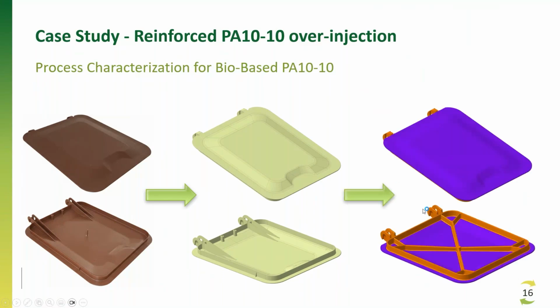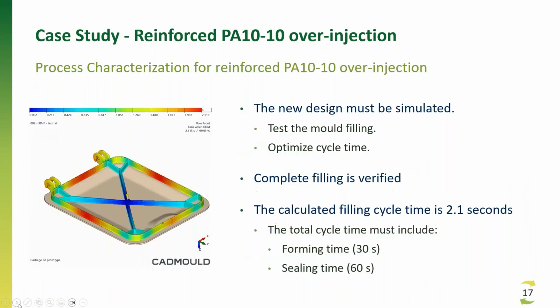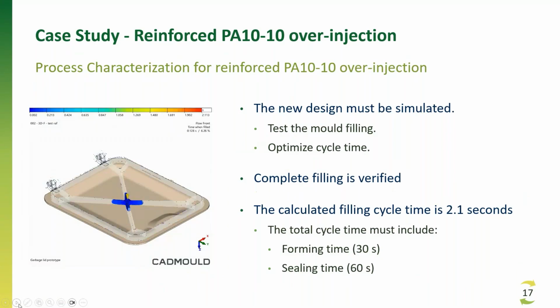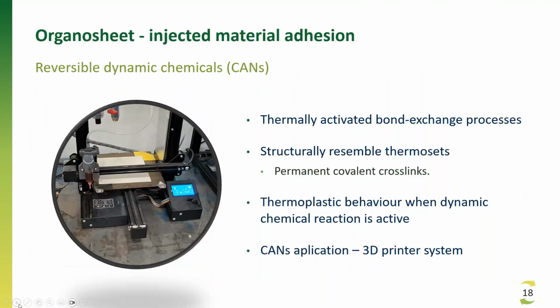Now, you can see here that what we did was this change. And what we decided was to put some ribs, and we are going to use the epoxy developed by Camille in the interface between the laminate and these ribs. The simulations verified that it was possible to do it with our injection point. This is the filling, and here is the main point: how to prepare these materials and how to put this bonding material into the laminate.